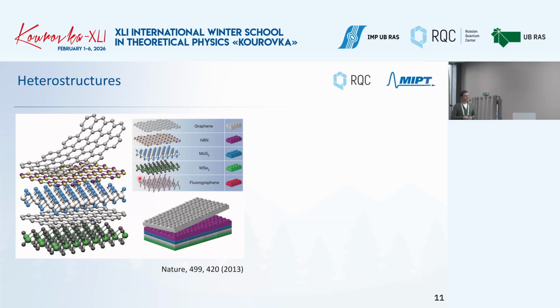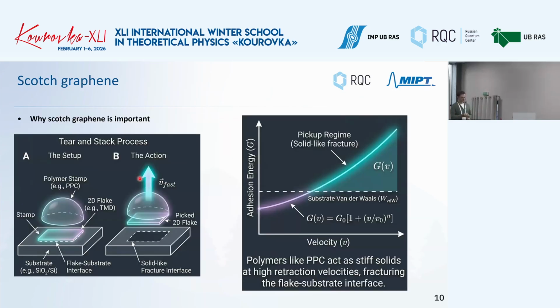Just one thing to mention here, I will go one slide back. It's written why Scotch tape graphene is important. It's important because, basically, if you want to obtain a very clean sample, a monodomain sample, you must use, unfortunately, this handmade polymer process. Exactly this is still what's happening now in the lab. If you want to have a very nice device, if you want to study new physics, very clean phenomena, something very peculiar, you still need to make your material by hand, unfortunately.